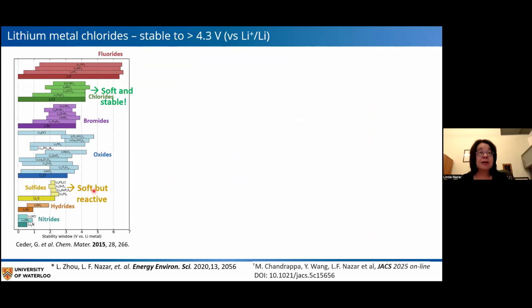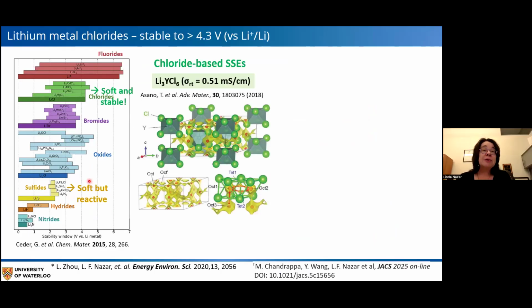So these are soft, the sulfides, but they're reactive. And the point is that the halides are just as soft. In fact, they have better mechanical properties in many respects, and they're stable. And they were introduced by a group at Panasonic, Asano et al., and they took this lithium yttrium chloride and effectively ball milled it to increase the conductivity towards that benchmark of 1 millisiemens per centimeter. And this caused a lot of excitement, I think, when this paper came out.